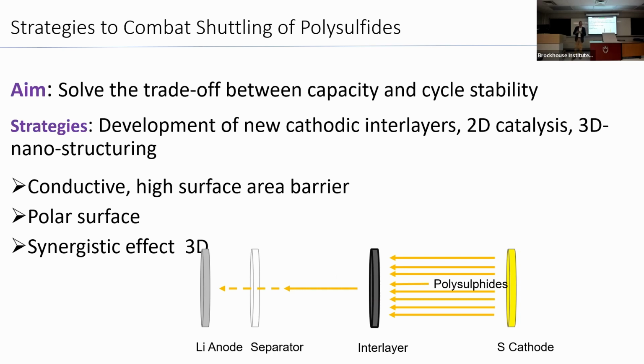So cycle stability must be predictable. It must guarantee for most of the batteries, certain amount like 2000 might be the aim, for example. And how can we guarantee it? So therefore, it requires new ideas. One idea is because we know the shuttling takes place because there's nothing stopping the diffusion. As I said, to some extent, we don't want to stop the shuttling because that is what actually is electropolishing the dendrites. So we want the shuttling to take place at a minimum amount, maybe a few percent, but not freely under concentration gradient and electrochemical concentration gradients.